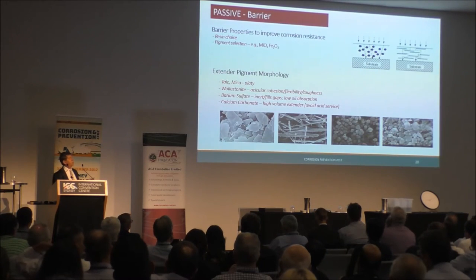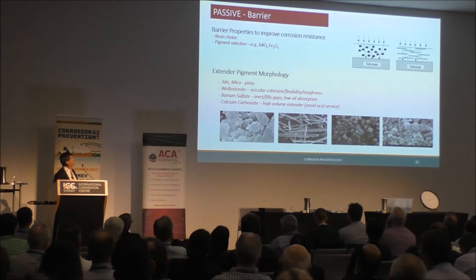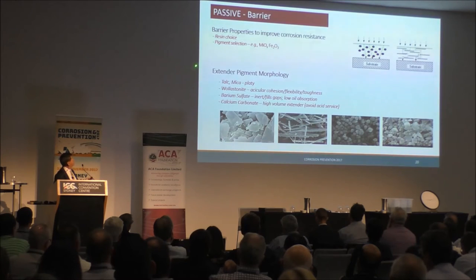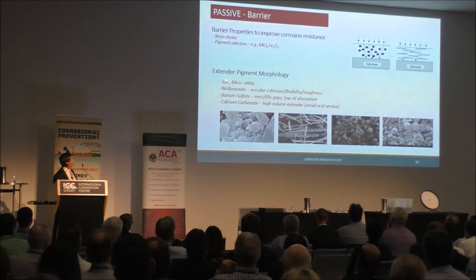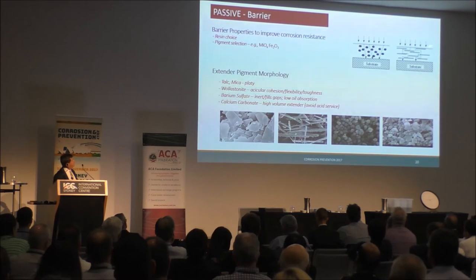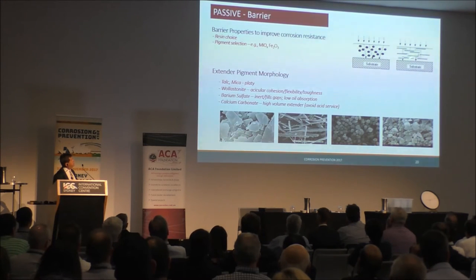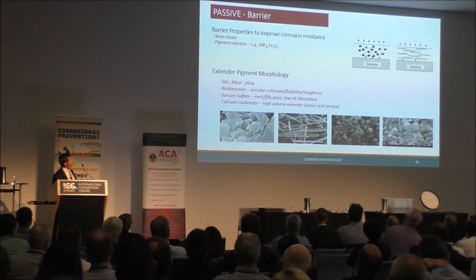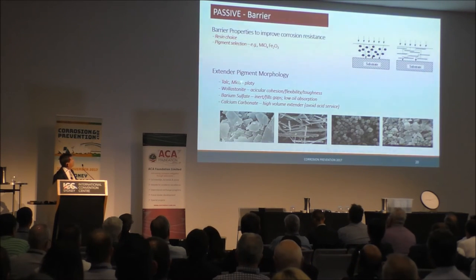So, while we talk about passive films and barrier effects, I'll just mention the critical factors associated with the pigments that you use. So resin choice is very important, but so is pigment selection. And you can use different types of pigment, and sometimes they're described as extender pigments: talcs, micas - platy. And in the paint that you've designed, if you put flat plated pigments in the paint, you can slow down the rate of water transport through the thickness of the film by making the water path much more tortuous than if it's just spherical particles, say, in the same formula. So that's a very important factor to keep in mind when you're designing the paint.